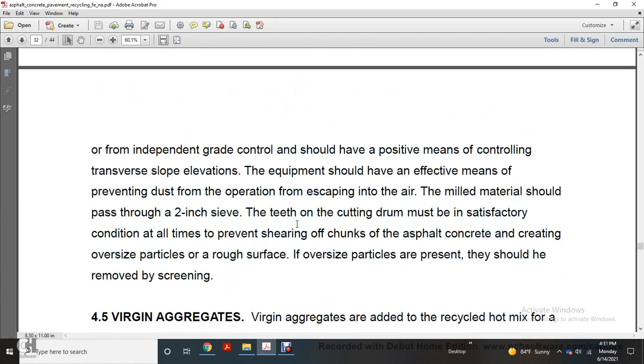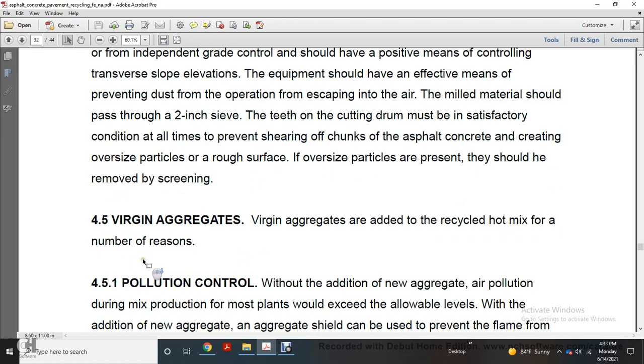Independent grade control should have positive means of controlling the transverse slope and elevation. The equipment should have effective means of preventing dust from the operation. The milled material should be passed through a 2-inch sieve, with the teeth of the cutting drum kept in satisfactory condition at all times to prevent shearing off of chunks. Asphalt concrete crushing overall produces a rough surface, and oversized particles should be removed with screening.